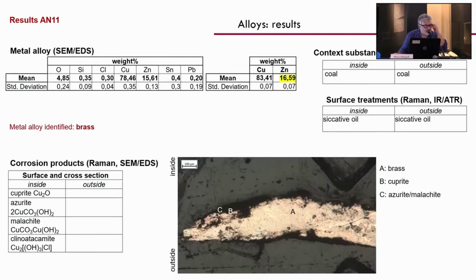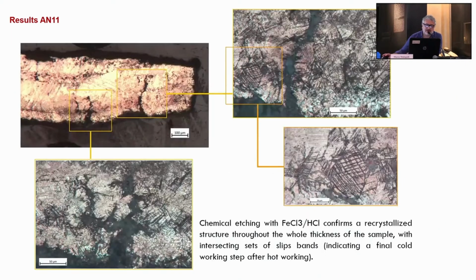And the last was a very important cross-section, because in this case, we had a very low mineralized part that you can see in C and B. So in this area, we had a mineralization process of the alloy, but all the cross-section was made of metallic brass, metallic alloy. So that was very important for our colleagues from the University of Bologna. They work in the metallographic process, so to have this kind of thickness helped them to analyze the characteristics of this cross-section.